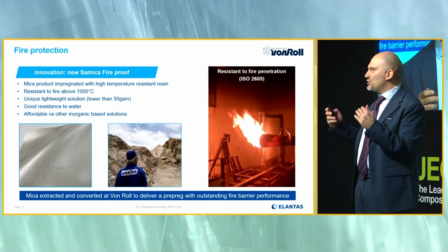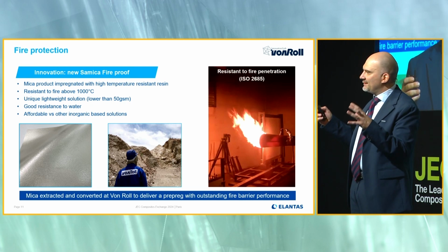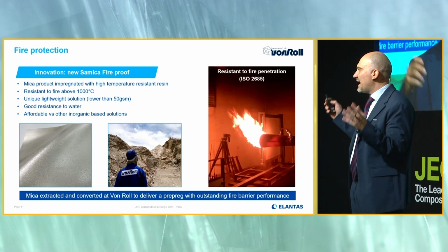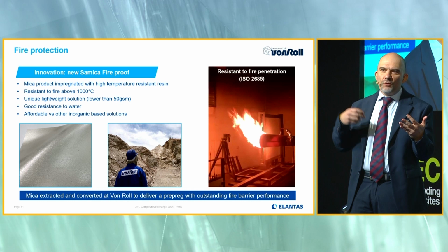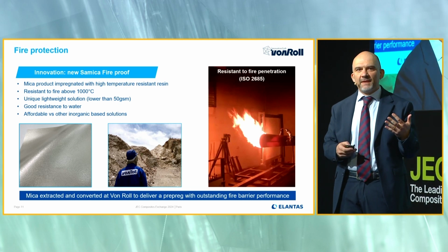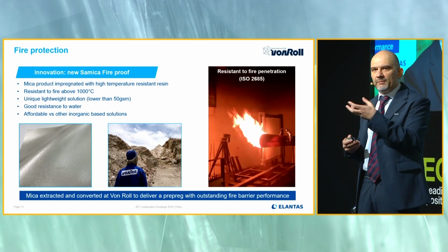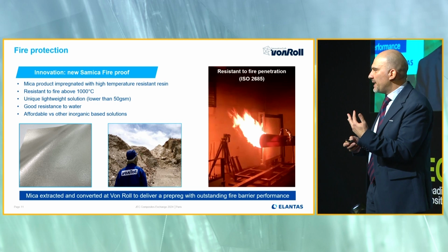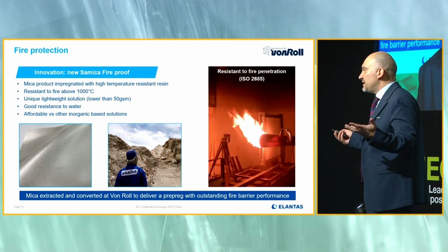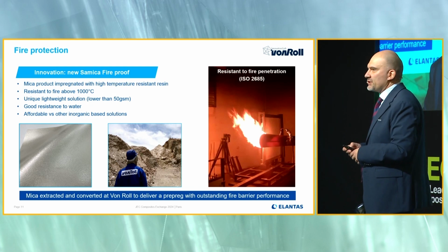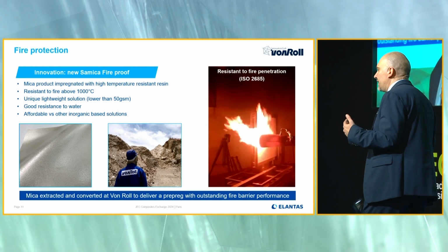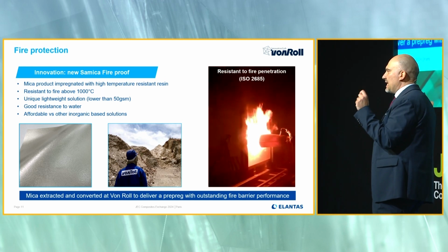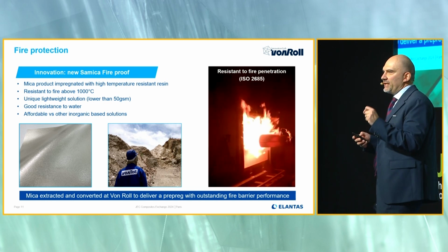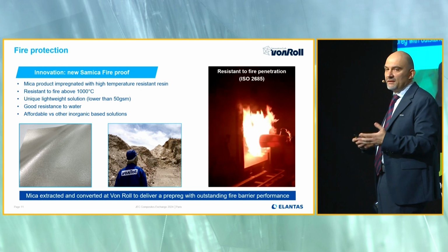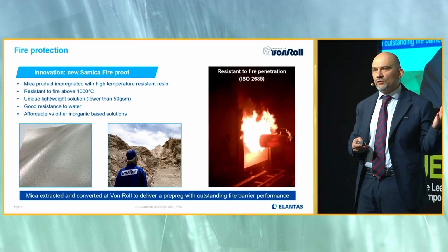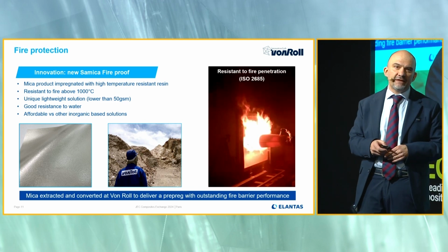It has the key advantage of merging the sustainability targets that we have, for example the use of natural resources, with the possibility to achieve very high performance. In fact, this is a product which is extracted from the land and is transformed into a product which is safety relevant for the aviation industry. Even at 0.1 millimeter thickness, it has such good fire barrier characteristics that it can survive very severe fire scenarios, like the one in FAR 25.853 part 3 or